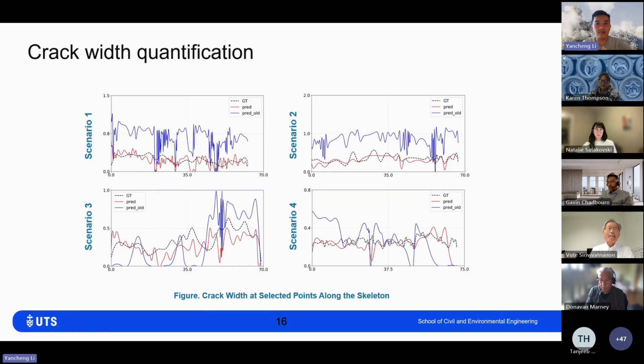We also compare with each individual crack. Over here we have the ground truth, which is the dashed line, the real depth and width of the crack along the length of the crack. The pred old means the zero shot prediction. You can see there is quite a variation from the ground truth, but the fine-tuning result is very close in matching the result over here. This pattern appears in all the scenarios, so we can confidently say our result has been very good. Then I'm going to show you quantitatively how good it is.